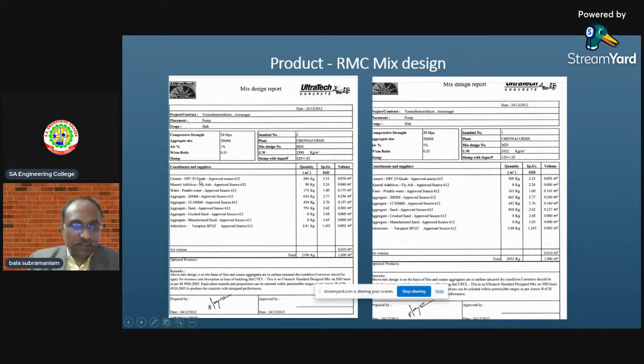Here you see the first, left-hand side mixed design report. It is M20 grade of concrete. Here also it is M20 grade. So both sheets represent the grade of concrete as M20. Unit weight of this could vary between 2,300 to 2,500. See, here it is 2,390, and here it is 2,435. That's a small variation. It's fine. And other parts like slump, everything is fine. And the compressive strength here is 20 MPa, and here it is the same 20 MPa. But the significant difference is this.